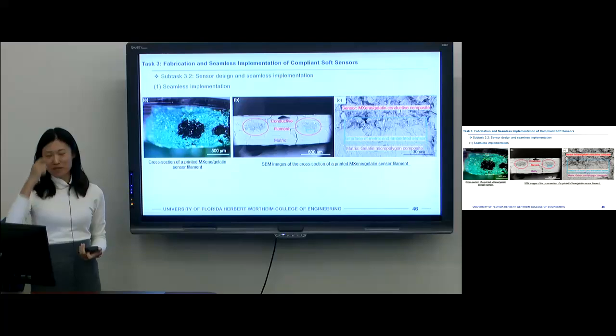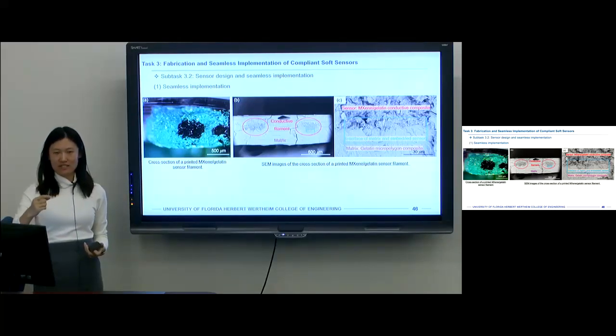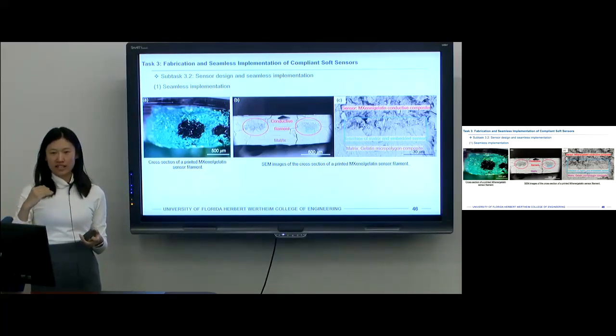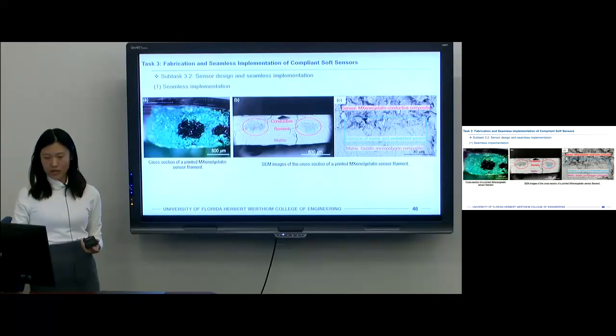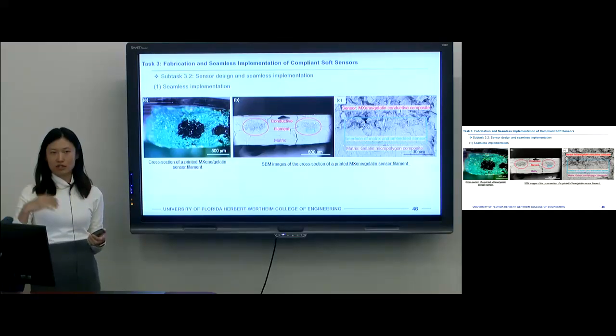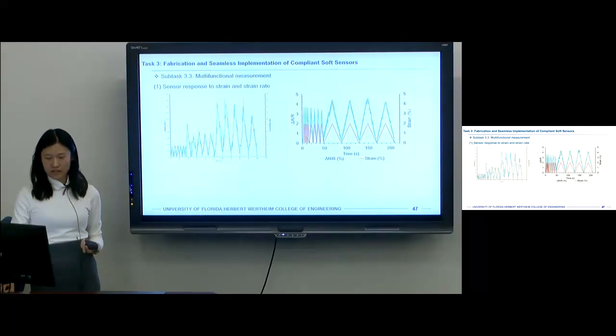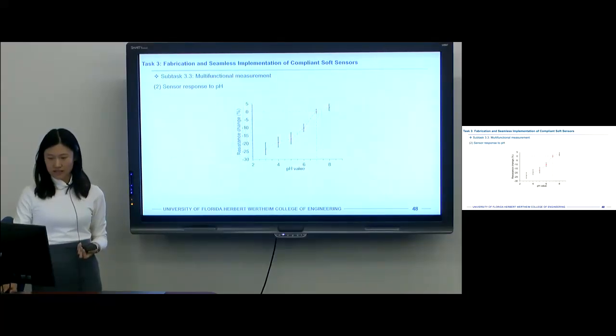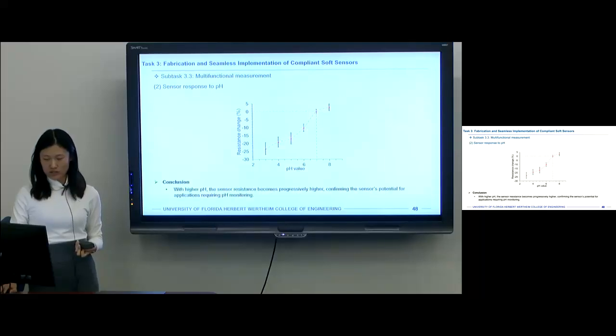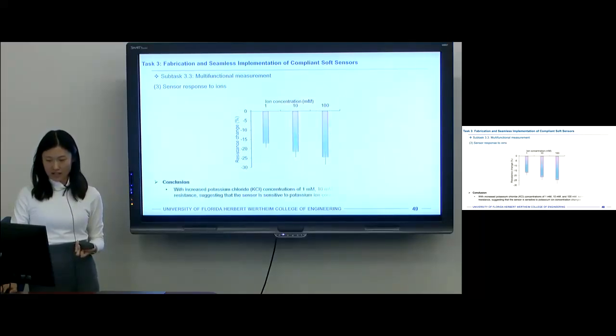As we mentioned earlier, a rigid sensor will have an interfacial gap because of interfacial mechanical mismatch. Here we have the gelatin MXene material, which is very soft and similar to the brain material, so there will be no interfacial gap, as shown in the SEM image here. Here is the response to strain and strain rates, and the sensor response to pH and to ion concentrations.